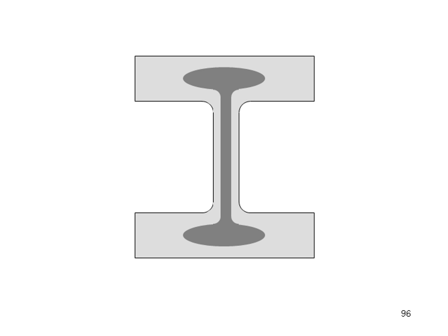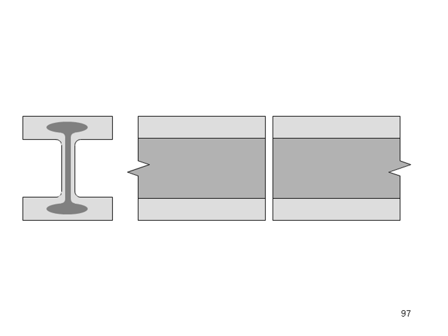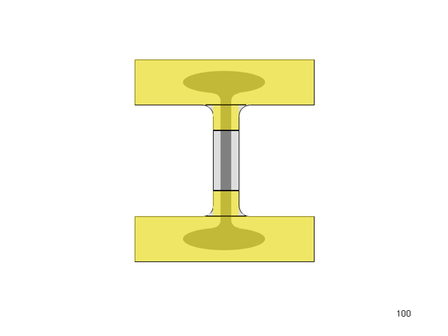Well, let's look at a tension splice. Now, in order to make a tension splice, I would normally cut weld access holes, and that allows me to place the backing in place. Of course, I have to bevel the flanges in order to receive the weld metal. Now, normally that kind of working is done with thermal cutting processes, and what I want you to see is that I'm thermally cutting on the flange area, some of the web to flange area, and even the cutting process is introducing residual stresses, and I'm working the steel, including the core region. Now, when I go to weld on it, I'm going to be welding into that core region as well.